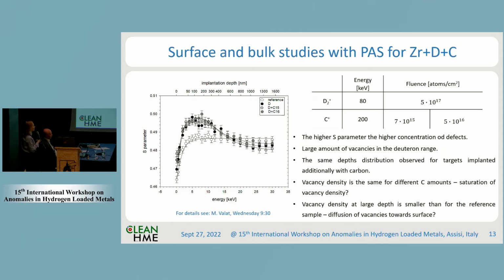Okay, and to be honest, we really think that now we understand with our theory and our understanding of the processes that are involved what is happening with the screening. So for zirconium, we have good values experimentally that agree with theoretical values. And we know that sometimes the screening energies are much, much higher. So we think that the reason for that is the amount of impurities, of vacancies, of crystal lattice defects that are there due to the beam irradiation in this metallic target in which we study the DD reactions.